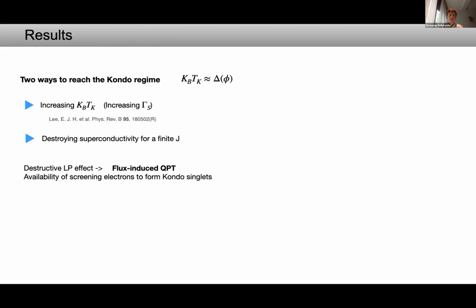So there are essentially two different ways to reach this Kondo regime. The first is by increasing the Kondo temperature, which can be done by increasing gamma S, the coupling to the superconductor, as was done by Eduardo Lee et al. in this paper. And another possible way to do that is to destroy superconductivity for a finite exchange coupling constant.